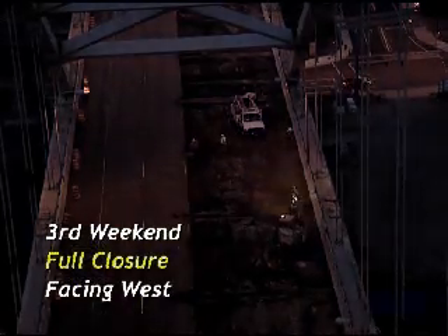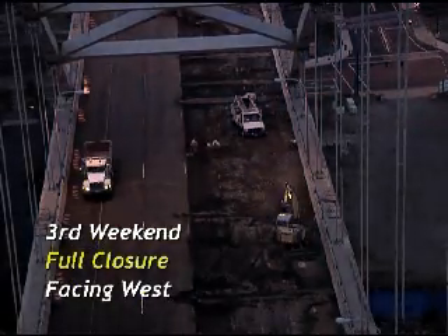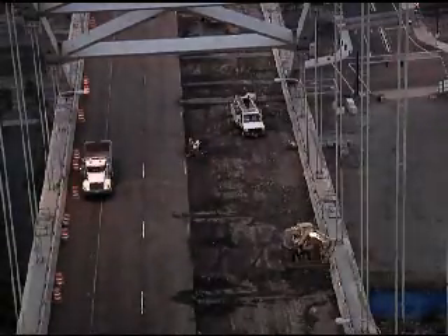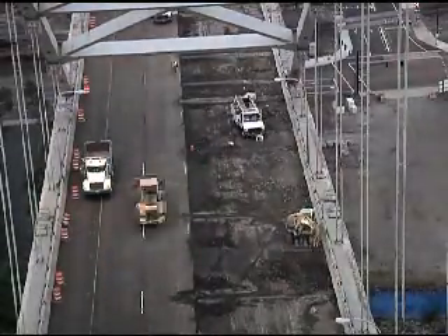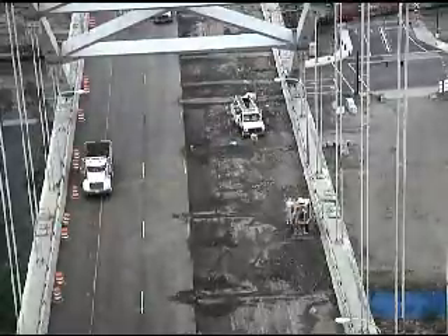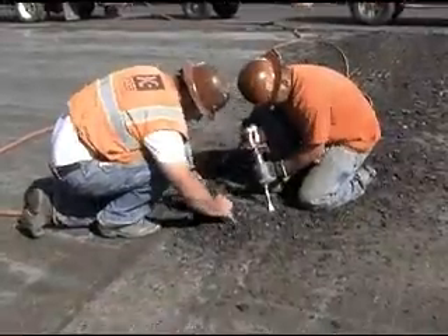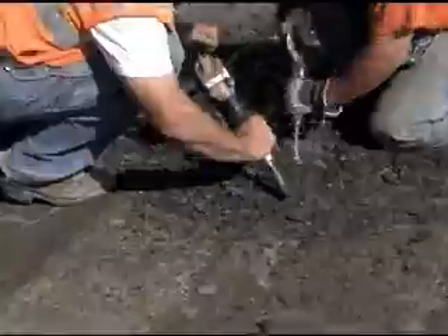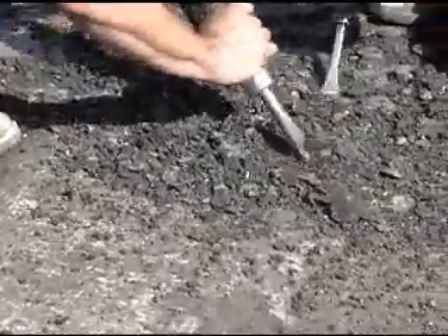The process of removing the old epoxy asphalt off the bridge deck was very painstaking. The contractor had a labor force upwards of 40 people, doing everything from operating the equipment to laborers using hand equipment and chipping around every single bolt in the splice plates on the steel deck. We estimate there were over 56,000 bolt heads that had to be cleaned around. Each of the bolt heads has 6 faces, and each face had to be chipped off, cleaned, and basically taken down to bare steel, bare bolts.